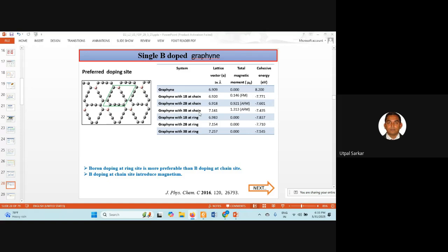So this is the calculation for boron doping with different concentrations and at different places, chain or ring. Okay, so lattice vectors change, and you see here that BN doping does not give you any magnetism. However, with only boron doping, boron doping at a chain site gives magnetism here. Okay, so they are magnetic in character. However, boron doping at the ring site does not give rise to any magnetism. Okay, and these are the corresponding cohesive energies.